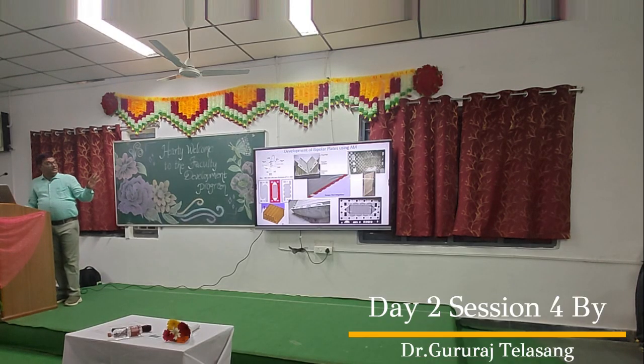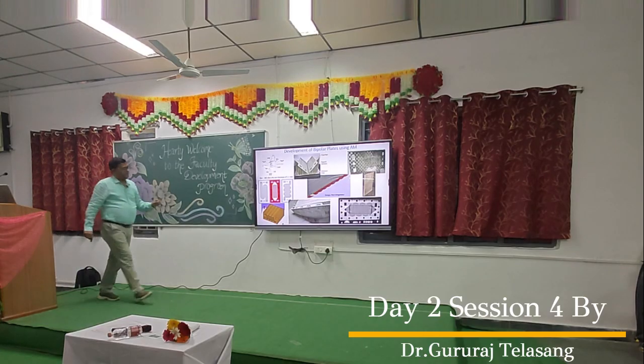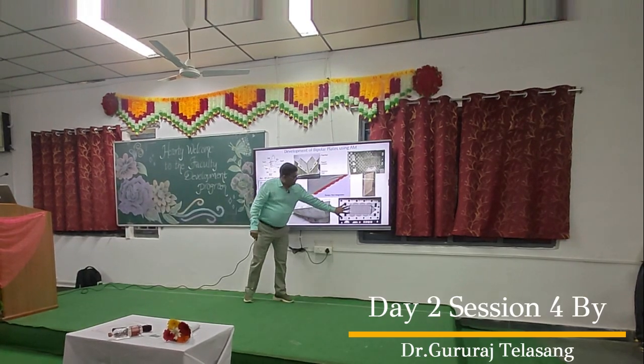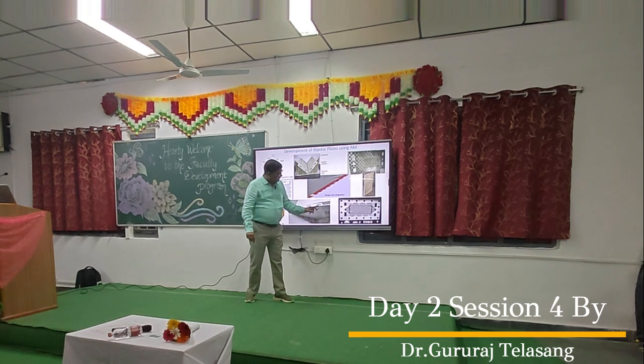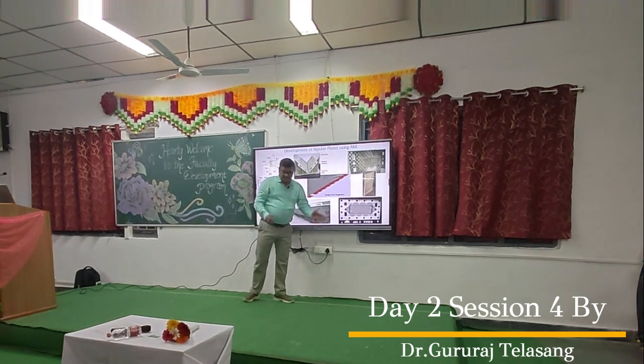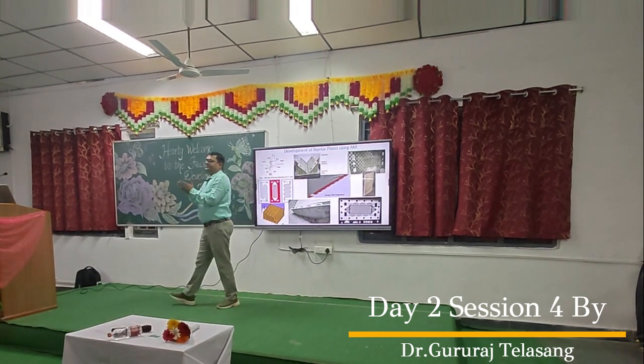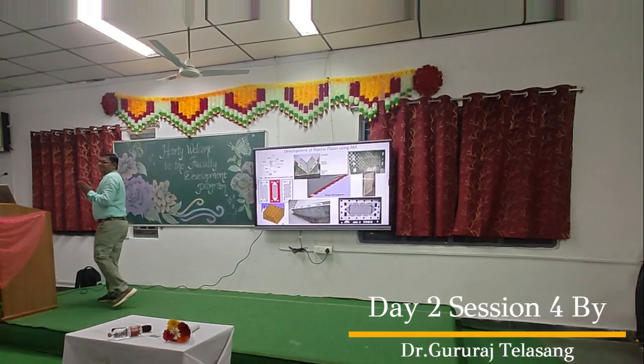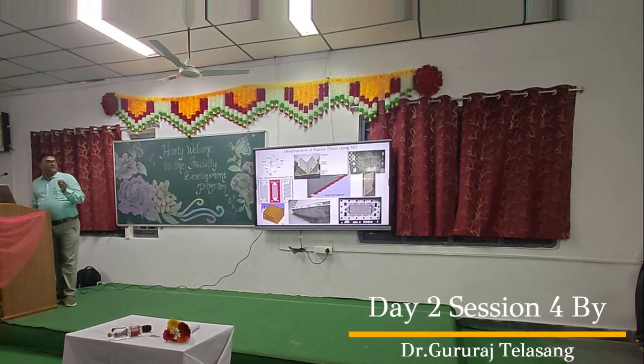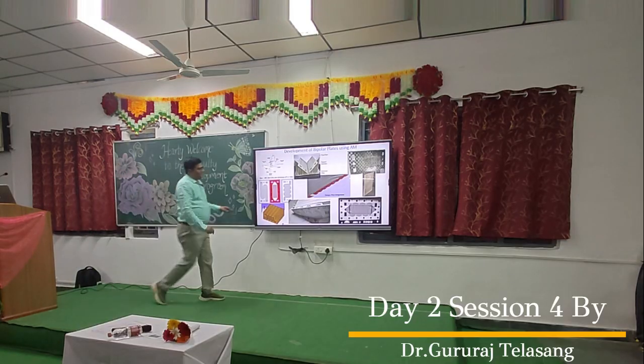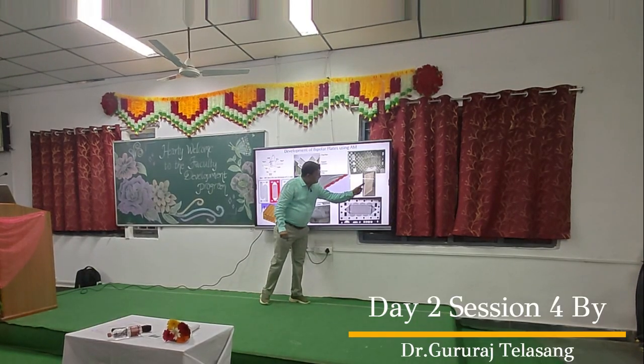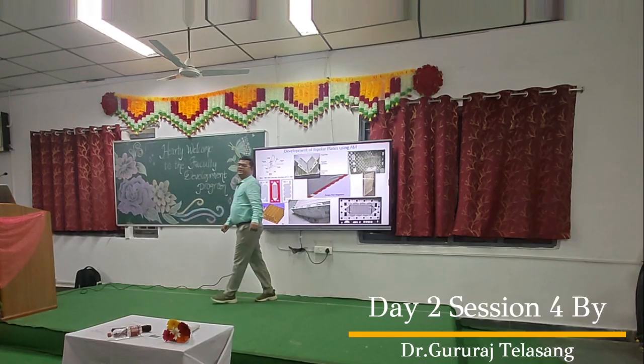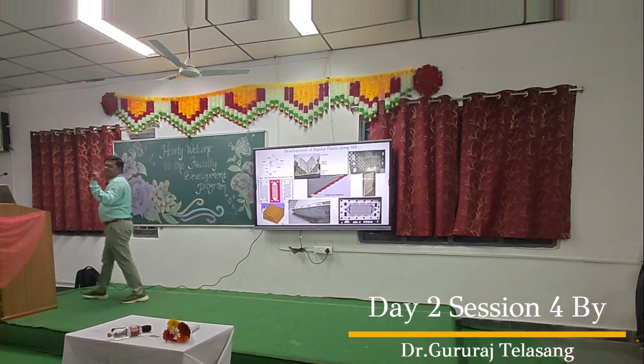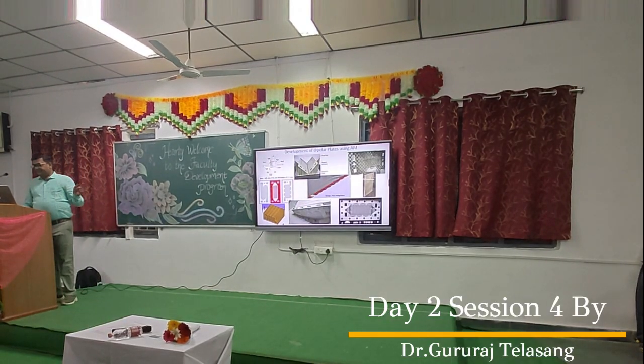This is another complicated one. So I will just show you the X-ray here. This X-ray has, this is a 2.1 mm thick plate. These channels are in 3 layers and placed 100 micron apart each. Micron. There is a slit here. Can you see here? Thin slit here. That is a 300 micron slit in a 2.1 mm thick plate. It's used in a hydrogen oxygen fuel cell bipolar plate.